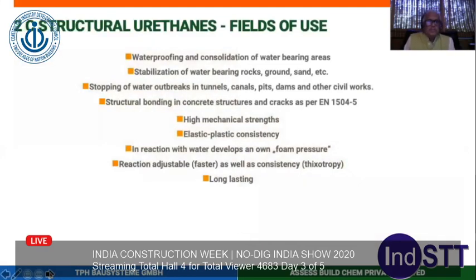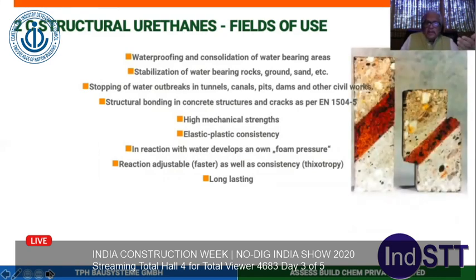And then comes the most important, the two component structural polyurethanes. Structural polyurethanes develop a strength of 70 to 80 Newton per mm square. So you can replace epoxy injections with them, even in cases of dry cracks, so that you don't have to mix too many materials. They can be used underwater. There is no problem of hardening. They are not sensitive to moisture. Their foaming can be controlled from 1 to 15. They have very high bond strength and very high shear strength. And this is very, very important for either soil consolidation or force transmitting cracks. And these are the materials.